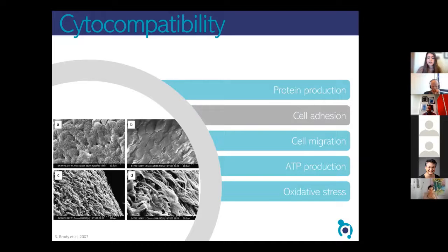Cell adhesion would also be very interesting in case, for instance, you're working with coatings. Some biomaterials are basically coatings that can promote a change in the behavior of several cells. And in this case, it was an ECM coating where cells were applied on top. And maybe you would do SEM just to see if the cells are actually attaching to the surface and see if there are any changes in their morphological characteristics. Or you would also like to see if there are any focal adhesions and if your cells are actually adhering to each other, and you can do stainings, for instance, for integrins or many other ways. But SEM is a very powerful tool and very, very useful.